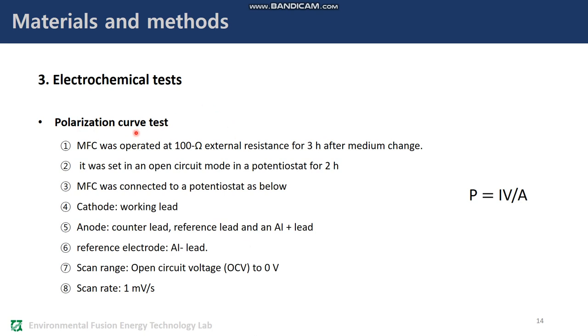Polarization test. For polarization tests, the MFC was operated at 100 ohms external resistance for 3 hours after medium change. Then, it was set in an open circuit mode in a potentiostat for 2 hours, followed by an electrochemical experiment. MFC was connected to a potentiostat as below: a cathode to a working lead, an anode to a counter lead, a reference lead, and an AI plus lead. Reference electrode to an AI lead.